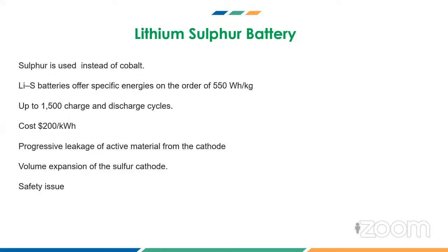And another problem is leakage of active material from the cathode. That means after some time the life is less, and the volume expansion of the sulfur cathode is one of the biggest issues. Volume expansion means during charging the volume of the battery is increasing, during discharging the volume of the battery is decreasing. So continuous expansion and contraction may lead to mechanical failure. So volume expansion is one of the major drawbacks of lithium sulfur battery.